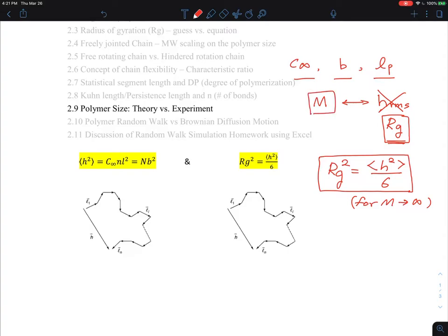They found out that the radius of gyration is proportional to molecular weight to the power of 0.5 in the melt state. That has been one of the major breakthroughs in polymer physical chemistry in the 1960s and 70s, using the neutron scattering experiment.